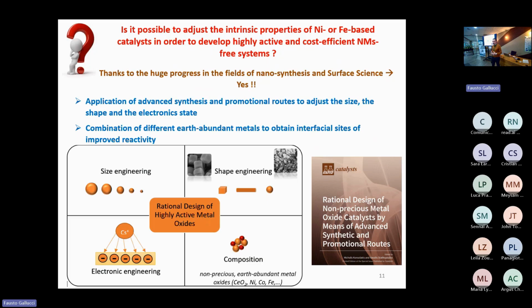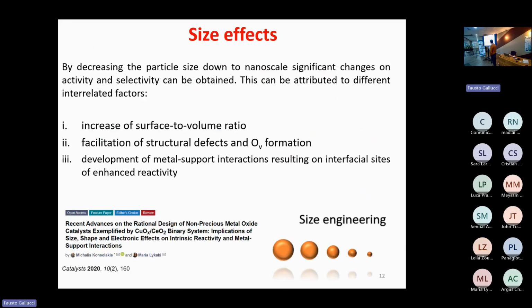Thanks to the huge progress so far achieved in nanosynthesis and surface science, the answer is yes. And this can be achieved by advanced synthesis or promotional routes at nanoscale and through the combination of different transition metals in order to take advantage of the synergistic interactions between them and from the interfacial activity. At this point, I'd like to briefly mention some fundamental aspects about size and shape engineering. It is well known that by decreasing the particle size down to nanoscale, significant changes in activity and selectivity can be obtained, and this can be attributed to different factors involving, among others, the increase of surface to volume ratio, the facilitation of structural defects and oxygen vacancies, and last but not least, the development of peculiar metal support interactions which result in interfacial sites of unique reactivity.